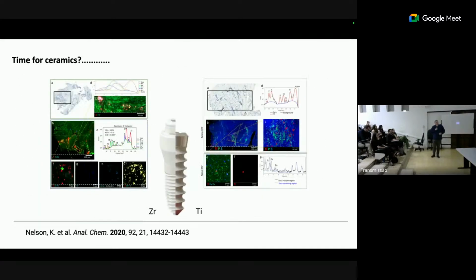The other thing that straight jumps to mind for all of those of you thinking I'm going to jump to zirconia implants is we've been doing some work on zirconia implants as well. And guess what? You find a load of ceramic debris, also on a very small scale. And so there's now a question of whether you're getting very minor low temperature degradation of that surface, leading to degranulation of the ceramic.